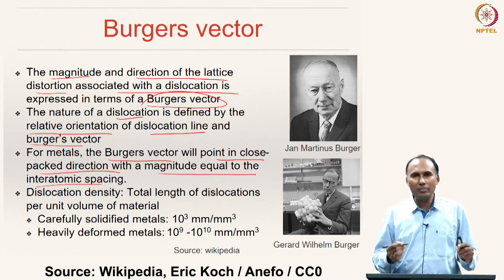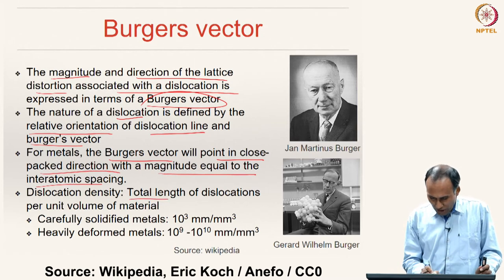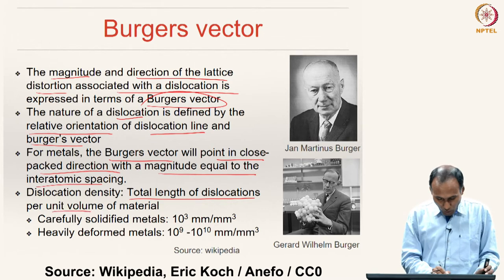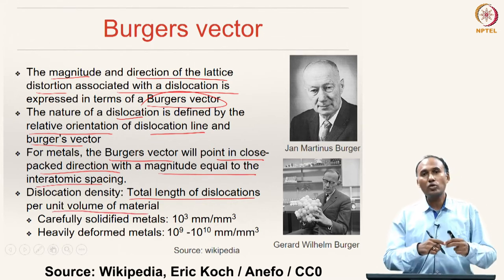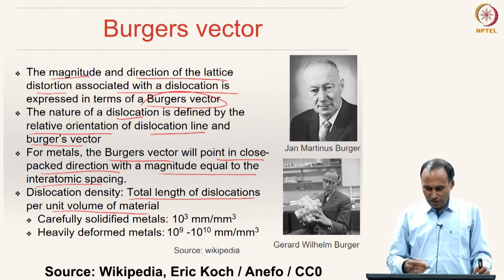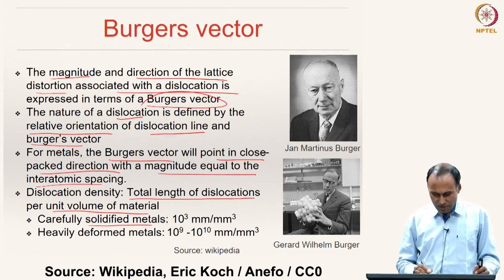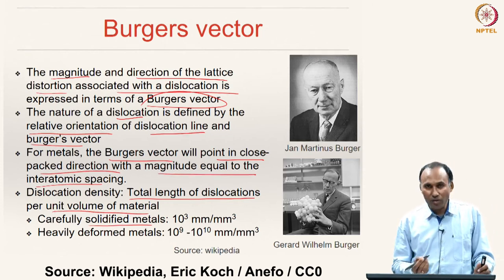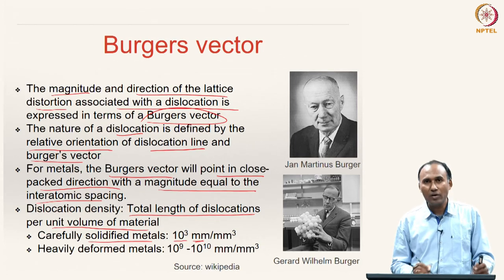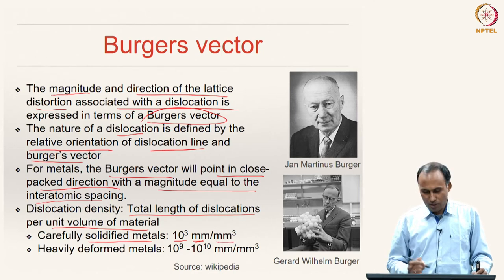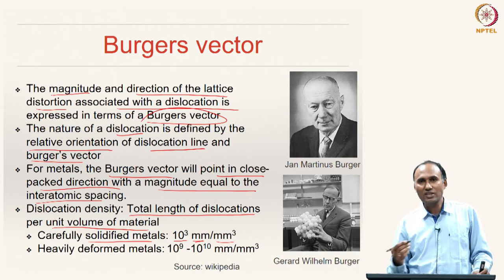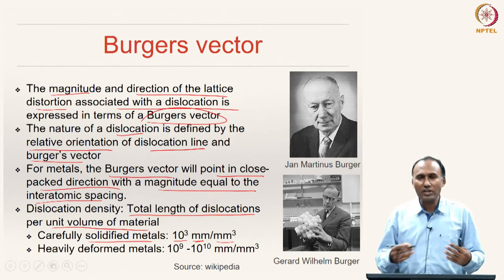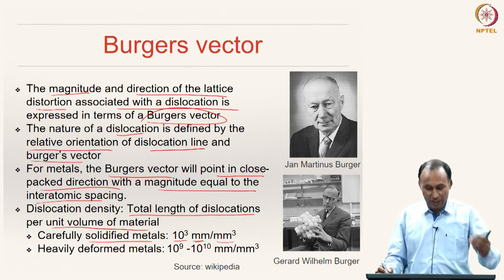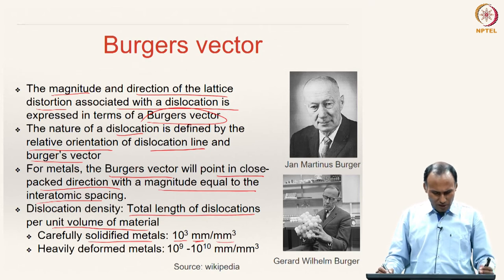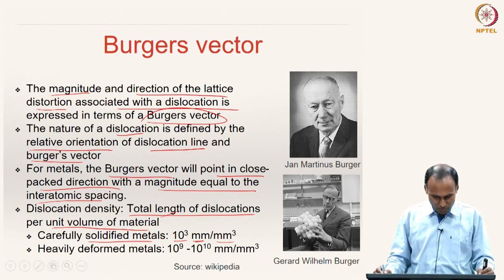And what do we mean by dislocation density? This is a quantity that describes the total length of dislocations in your material per unit volume of the material. So if you take a unit volume of material, what is the total length of all the dislocations? For instance, if you take a carefully solidified material, the dislocation density will be something like 1000 mm of length of dislocations per cubic millimeter of sample. So 10 to the power 3 per mm cubed is the dislocation density. Some people also describe the dislocation density as number of dislocations per unit area. That is also another way people describe it, but the better definition for dislocation density is the length of the dislocations per unit volume of the material.